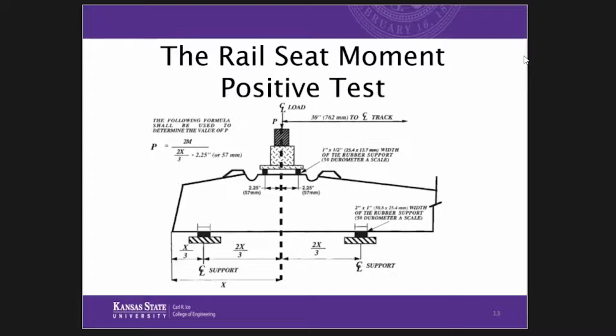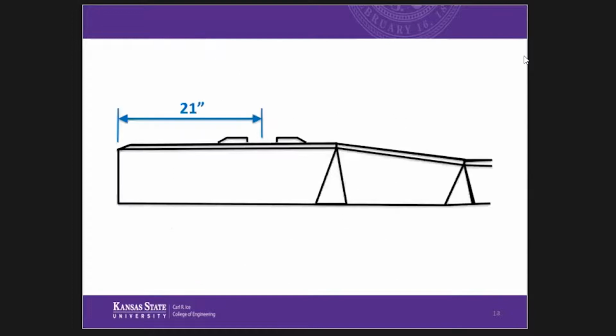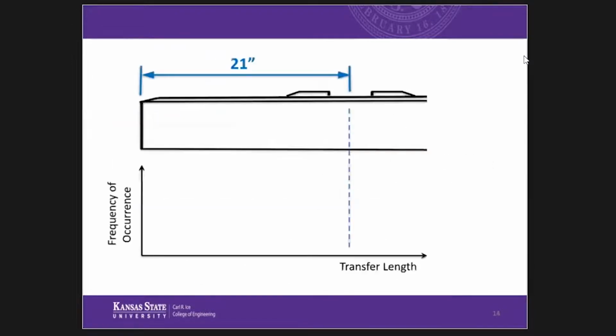And we want to verify that if that crack doesn't open up until the value we want, that ensures that at that point we do indeed have the amount of pre-stress force we want. And so oftentimes we talk about the rail seat being 21 inches from the end of the tie. And if we measure a single value, we get a single resulting transfer length. But that's only for that end of that tie.